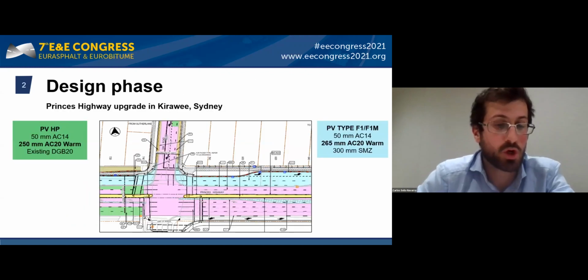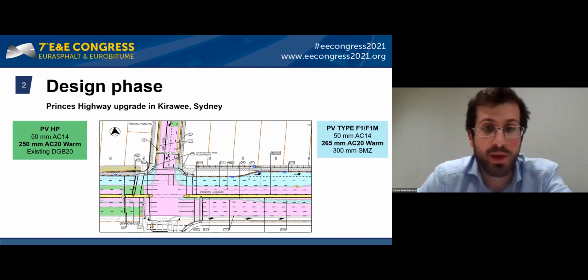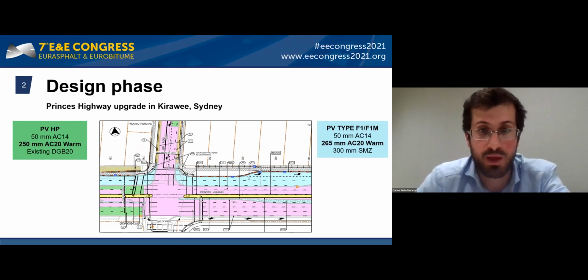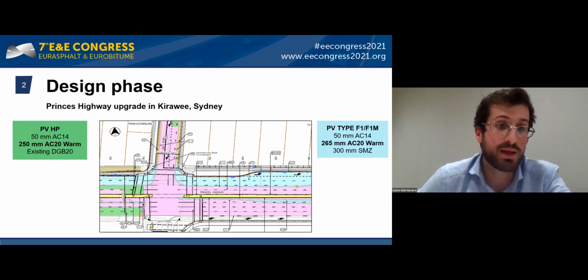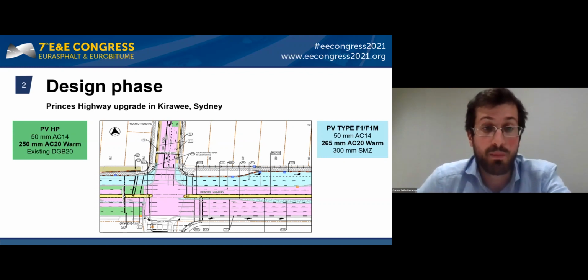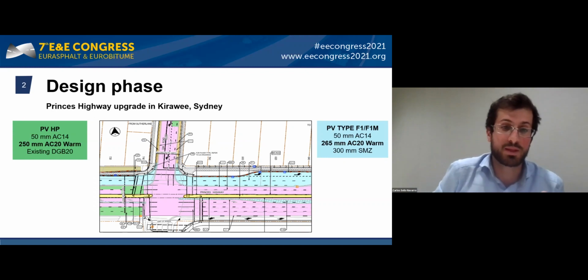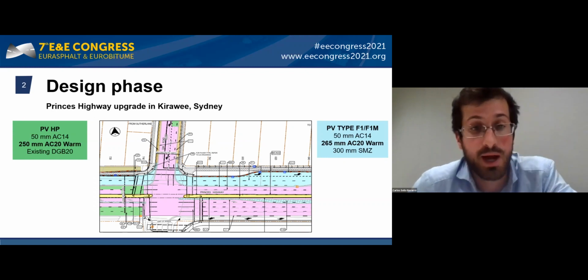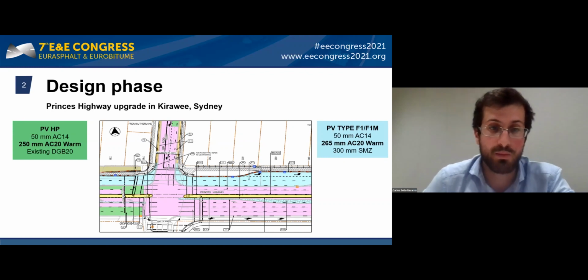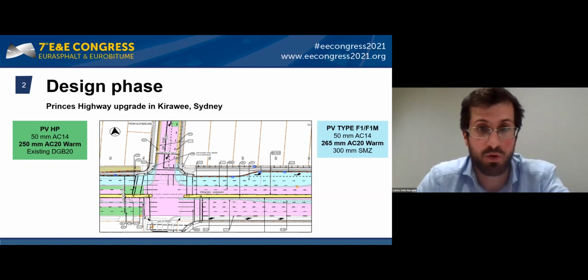Having this methodology in mind, we adopted it for a number of projects. This shows an example of the solution. We have a widening, and then also some treatment within the existing carriageway. The thicknesses we are talking about are around 310 millimeters. So the warm mixes for the rehabilitation within the carriageway were critical to be able to undertake the job during a night shift and open to traffic the following day.